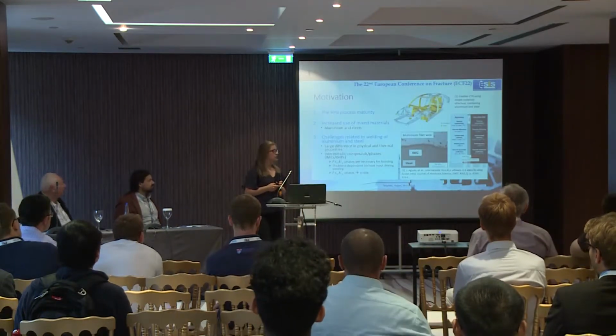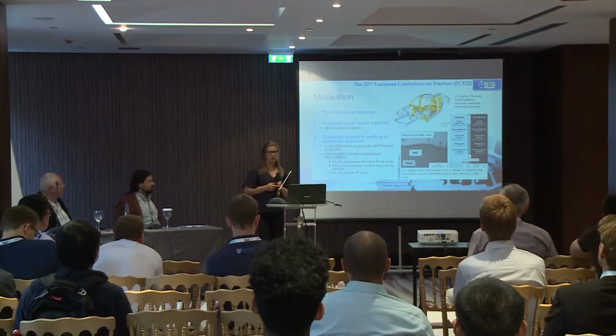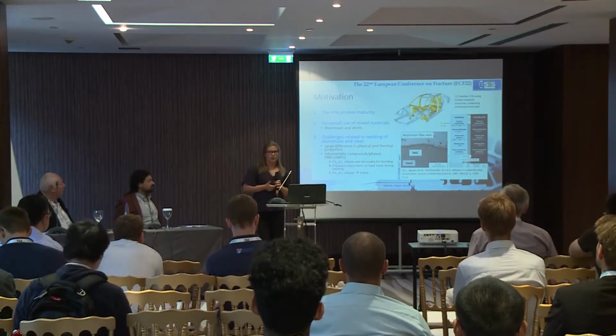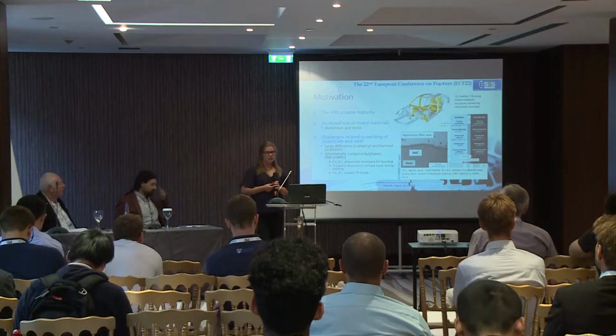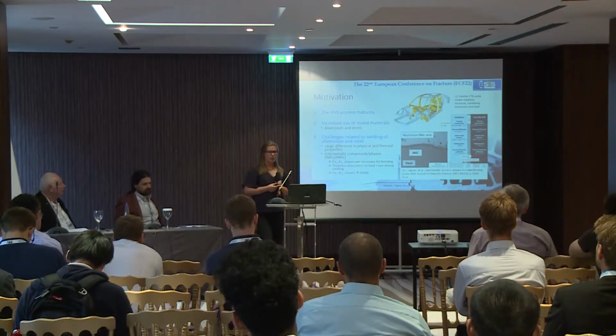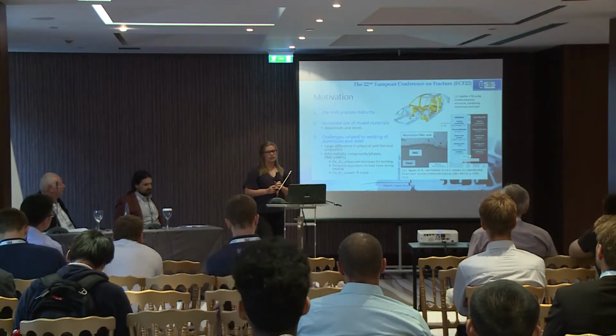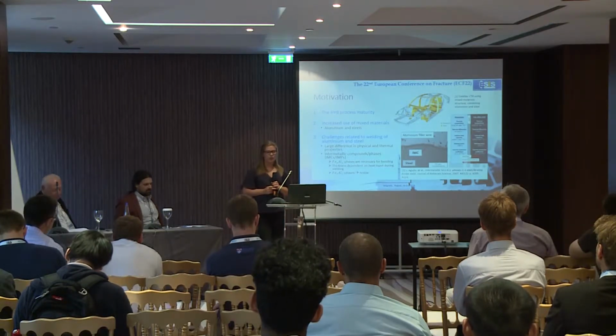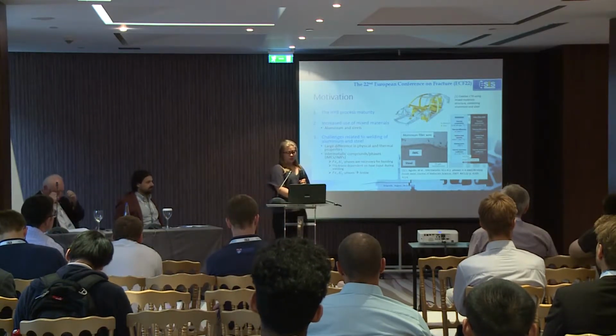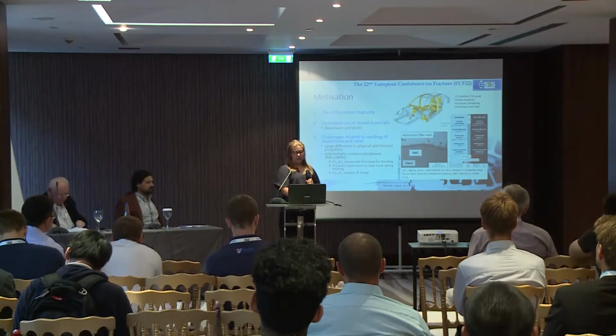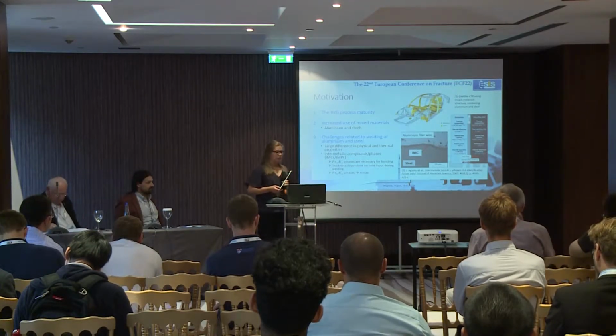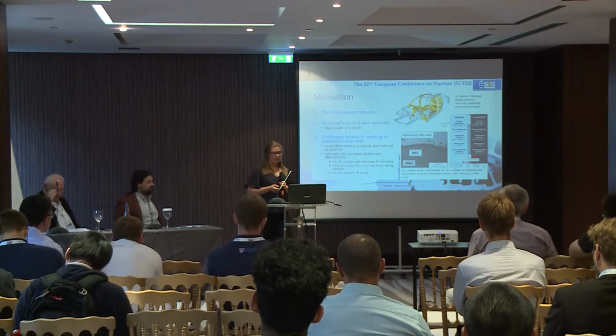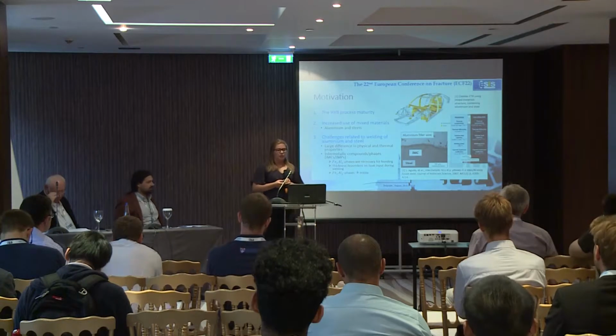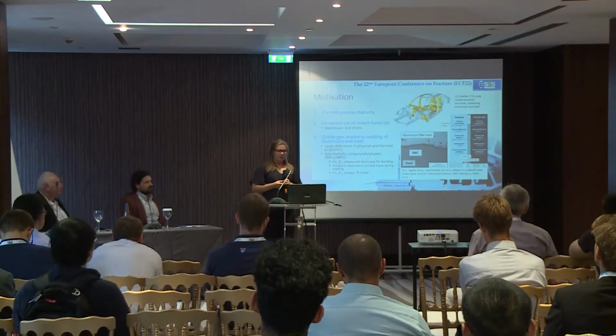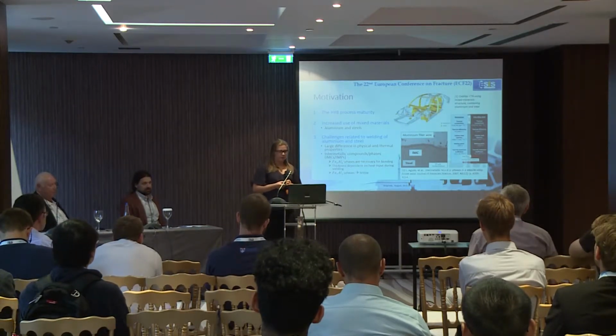So the motivation for this work is mainly 3 points: the maturity of the HYB process, the increased use of mixed material as aluminum and steel, and the challenges related to welding of aluminum and steel. The challenges related to aluminum and steel joining are mainly related to the large difference in physical and thermal properties, and the formation of brittle intermetallic compounds or phases along the bond line.